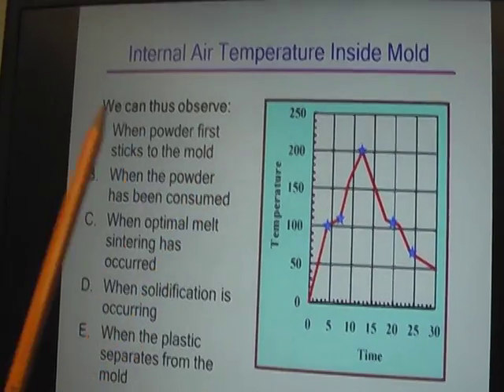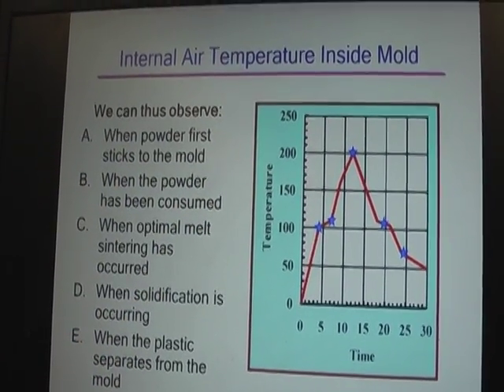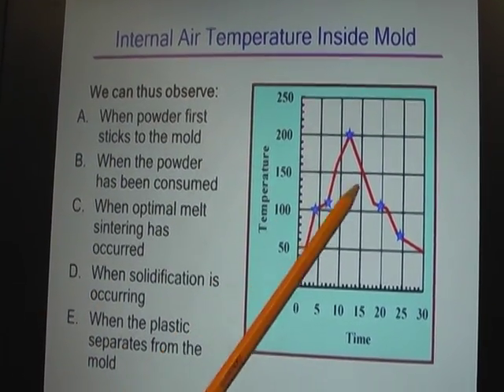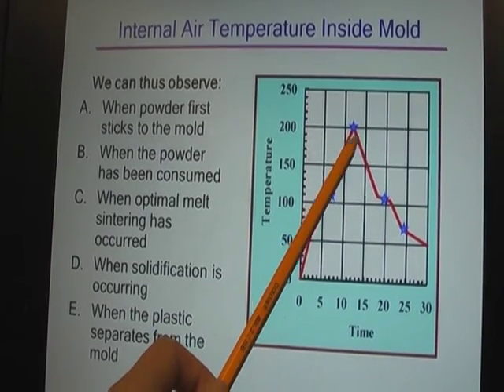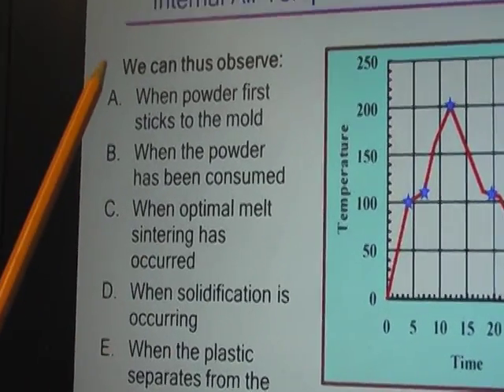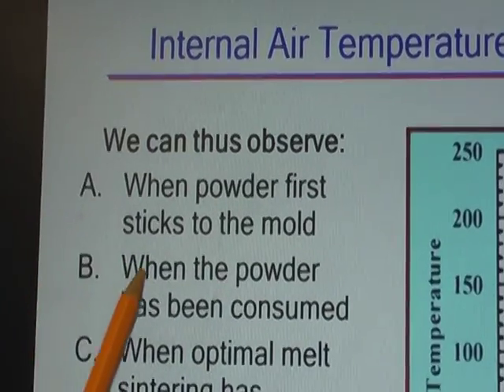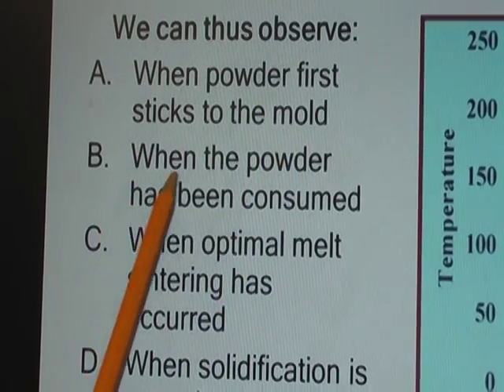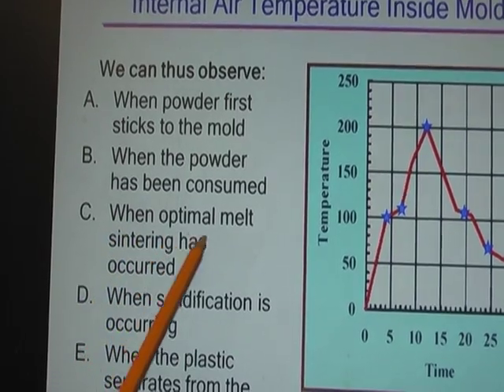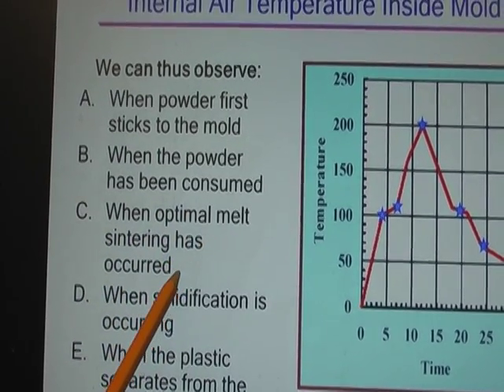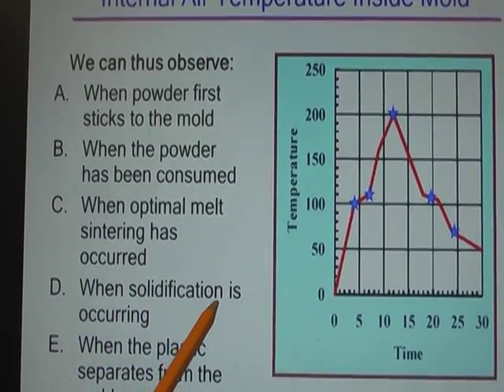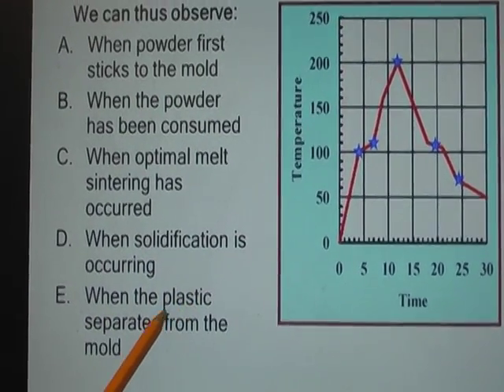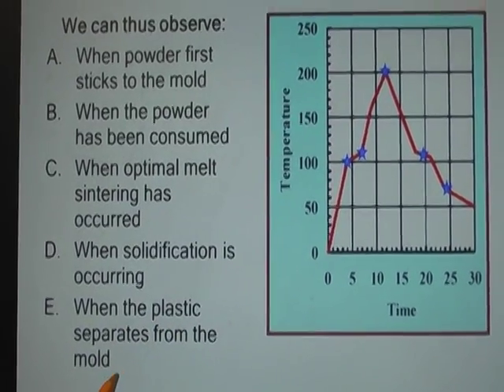And this is a summary of the internal air temperature inside the mold. And here are A, B, C, D, E, and this is what is happening at the different positions. At point A, the powder first sticks to the mold. At B, the powder has been consumed. At C, the optimal melt sintering has occurred. Then at point D, the material has already solidified. At E, your plastic product has already separated from the mold.